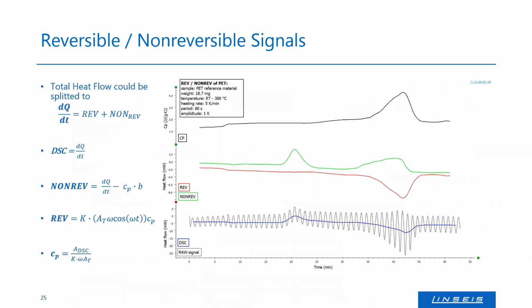I already mentioned there's some more information than CP we can receive with the temperature modulation. So here's the example again for PET with the reversing and the non-reversing heat flow. At the top we can see the CP signal, which we already discussed before, and in a bit you can see the reversing heat flow. So that's the CP upside down, and the non-reversing heat flow with the recrystallization and this second crystal perfection in the range of the melt.